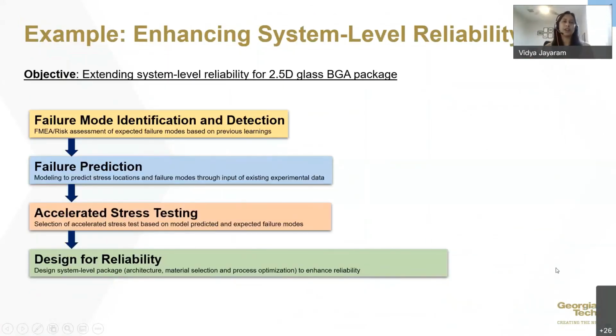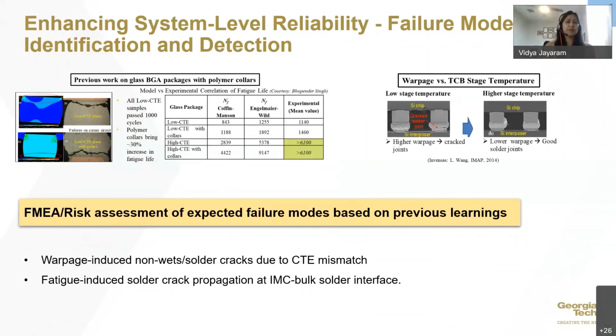So one of my projects at Georgia Tech PRC was to enhance exactly the system level reliability for a 2.5D glass BGA package. And we followed a similar structure to identify the failure mode, predict it, do some sort of stress testing, and finally design a system for reliability. So the first step, in terms of identification and detection, was to perform a risk assessment of what the expected failure modes would be based on previous learnings. So here we basically identified two main risk areas.